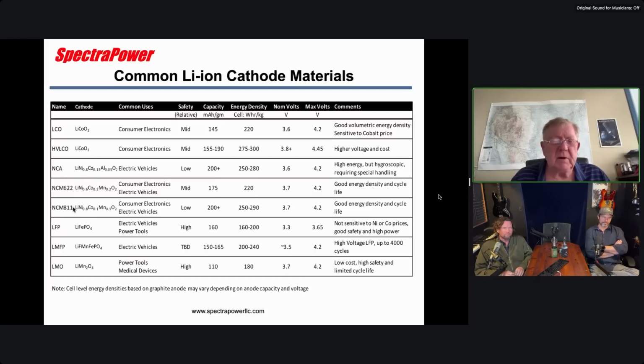811 is fairly recent, within the past few years. When it first came out, it had a lot of problems, unlike 622, which is very stable. And anyway, recently, 811 has gotten dramatically better. That's due to some of the Chinese manufacturers. And it's now actually a very, very good material. So you can see in terms of energy density what it does. It's somewhat comparable to NCA, but it'll take the cell energy density up to the high 200s range, whereas N622 is more like 220.